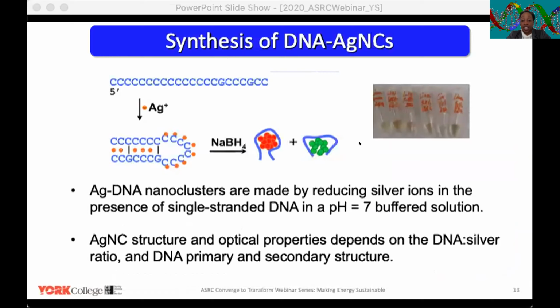So these DNA silver nanoclusters are made just by reducing silver ions in the presence of single-stranded DNA in a buffered solution. So it turns out that the charge carriers can tunnel very quickly through adenine and thymine pairs, but that rate of tunneling decreases the longer the strand is. And that's basically anything above 4 single-stranded base pairs. It also turns out that the charge carriers can thermally hop from one CG pair to another, and that is better for longer strands. And so the sequence chosen is then heavy loaded with a bunch of CG pairs. So these are the best hole charge transfer carriers.